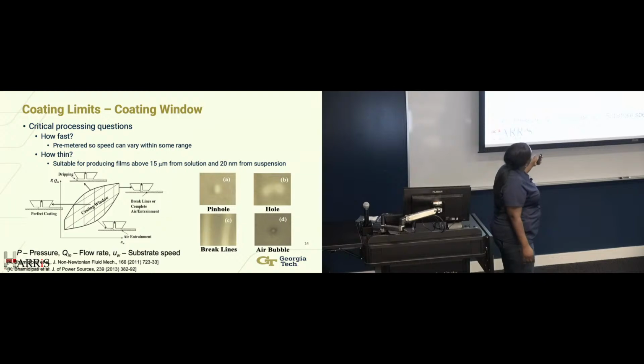So here, the coating window sits here. This would be the range or the area in which the material is coated well, and it should be pristine, no defects. Outside of this window, either I'm pumping too much fluid and I get an agglomeration of fluid on the back side of the die, just kind of flowing, and that could lead to spreading, and so your material is not going to be in the shape and form that you would ideally want it to be in.